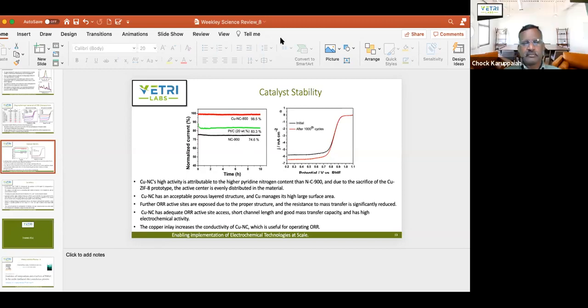And the other one I was thinking about, a more practical side comment, is that in addition to this efficiency being good with 4-electron transfer, it also impacts the membrane stability and other things. Depending on if you're using a polymeric membrane, you don't want peroxide impacting the stability of the membrane. So that's a good thing, to avoid the peroxide. Also the transition metal, I think we have a focus on the acidic PEM more, right? The Nafion membrane. So we don't know the compatibility of this catalyst in acidic conditions. All the studies were in alkaline conditions. Correct.